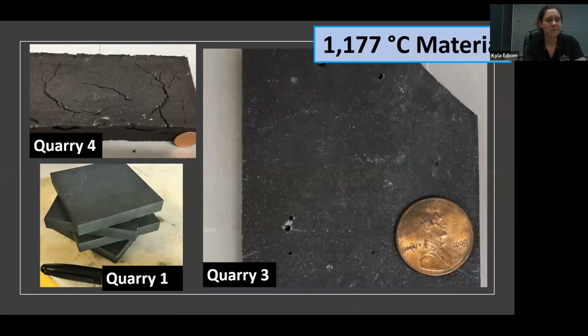The only way that you're going to be able to get that kind of stone is if you allow it to cool at a very, very slow rate. So obviously granite has thousands to millions of years to cool, where you don't have that kind of time in the kiln. So all that I did was bring that cooling temperature down as much as I possibly could, and for the shortest amount of time. And so that seemed to help, and we were able to make this really nice cohesive material.